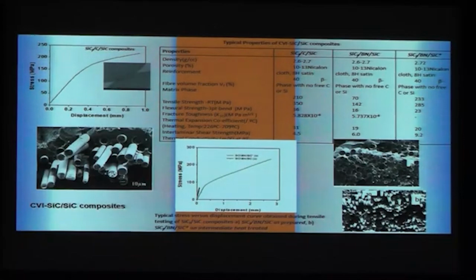So we have characterized the relevant physical, thermal and mechanical properties. And typically you can see the tensile property of this SiC/SiC, where the pyrolytic carbon interface is around 90 nanometer thickness, where you get a very good pull out. That means my fracture toughness is in the order of 20 MPa root m. And in the case of boron nitride interface, interface engineering is so important. You can see these two microstructures.